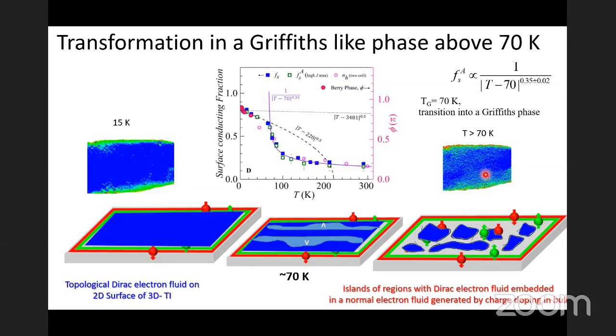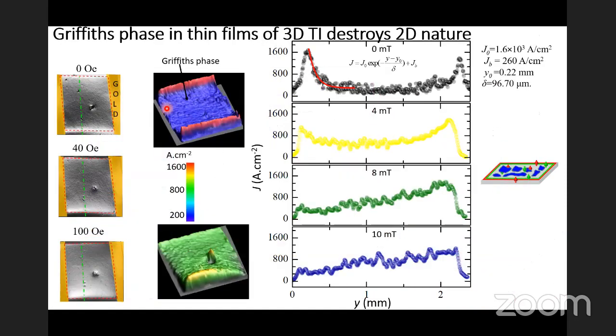in this 3D topological insulator. And what we believe is that a similar thing happens in thin films, because in thin films we feel that, because of the presence of a lot more disorder compared to single crystals, it already has a Griffiths transition temperature which is much below 70 Kelvin. And it is far lower than 70 Kelvin. So the system is already in these localized regions.